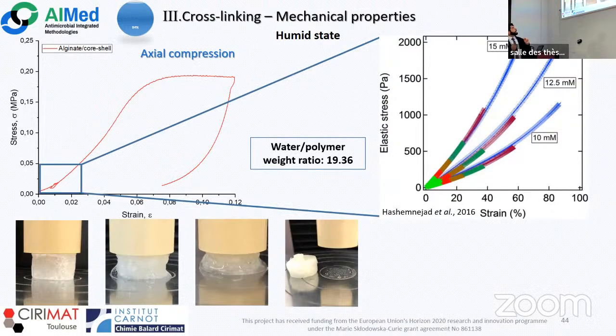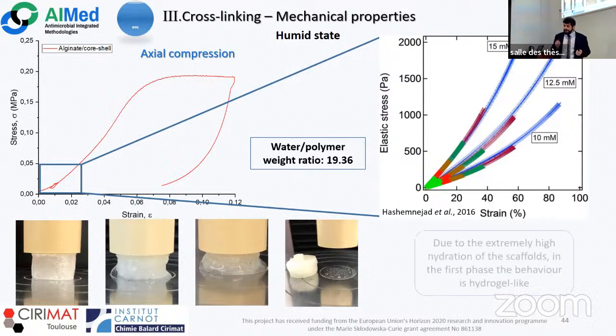not very expected thing, because we observed that this starting zone of the curve wasn't the one that we expected. Comparing that to literature, we noticed that this kind of slope was more similar to the one of the cross-linked hydrogel of alginate than to the one of our scaffolds. And we can also observe that after the first phases of the compression and after pouring out the water from the scaffolds, there is a change of the slope and we observed the mechanical behavior that we expected.